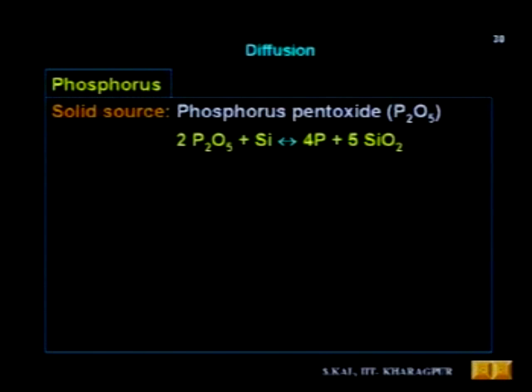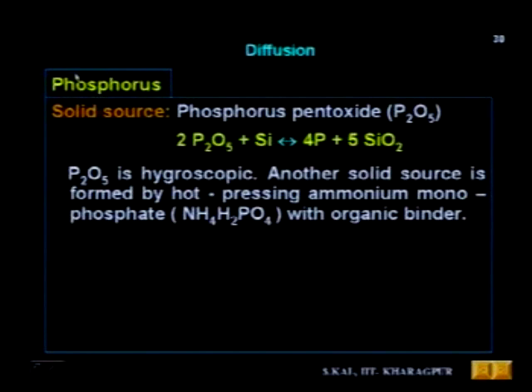Okay, this is one of the differences between boron glass removal and phosphorus glass removal. During pre-deposition, the phosphorus glass is completely formed, but in case of boron, the borosilicate glass is not completely formed during pre-deposition. For complete reaction, you have to go for LTO, or low temperature oxidation. Here you don't need that particular step. Now, P2O5 is hygroscopic in nature. That means it absorbs moisture.